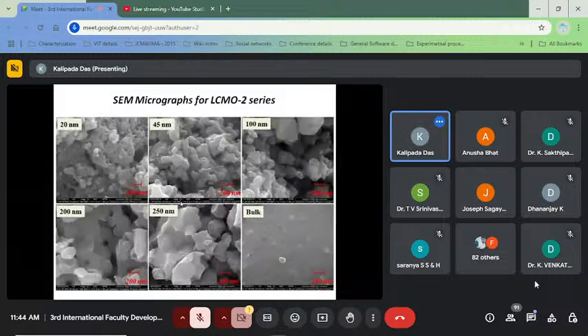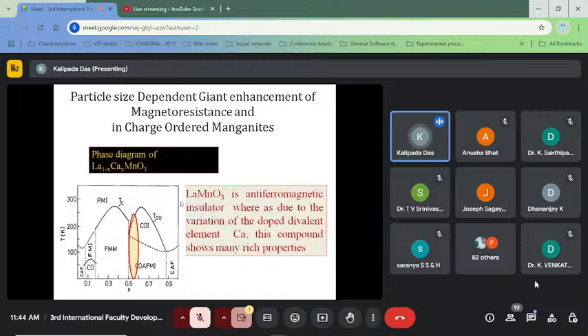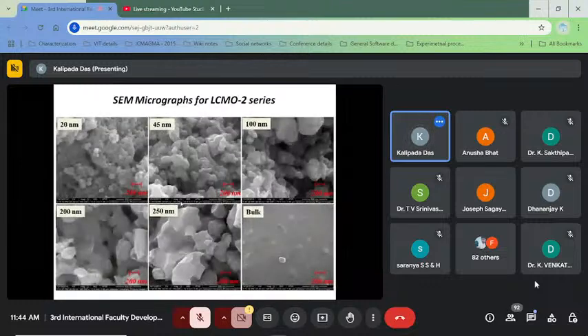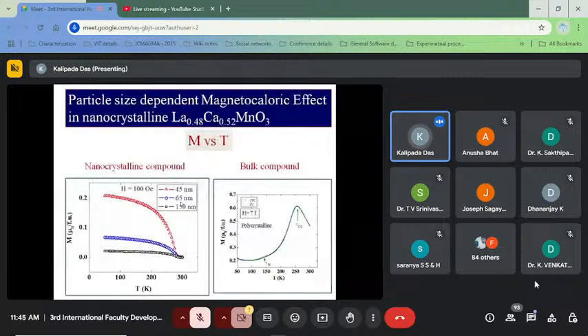And we have prepared another group of samples with a slightly different composition, 52%. That is also antiferromagnetic according to the phase diagram, which I have already shown in this circled region. So these are all antiferromagnetic phase in bulk. These are the 52% doping, and the same micrographs for 20 nanometer, 45 nanometer, 100 nanometer, 200, 250, and bulk. A different range of nanoparticles.